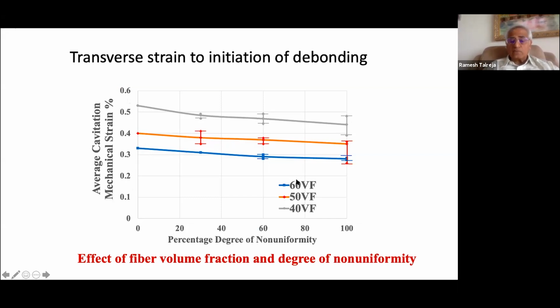So that value, what you see is that just over 0.3% in this case, it is a 60% volume fraction, which means there are larger clusters. As you reduce the volume fraction, clustering reduces, and therefore you have to do more work, or should I say less probability of finding a place where dilatation energy density becomes critical. Anyway, as you increase the non-uniformity, and this is sort of the new result, so you are quantifying now this effect.